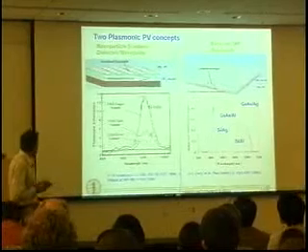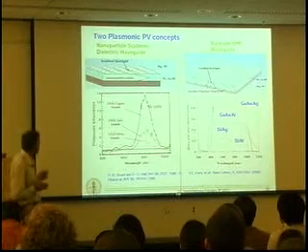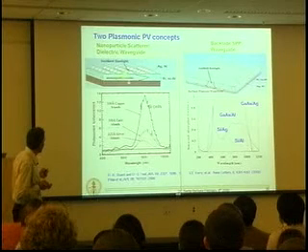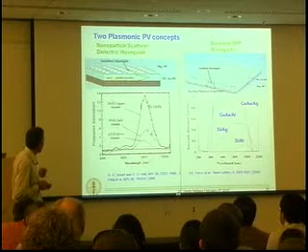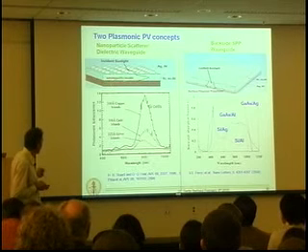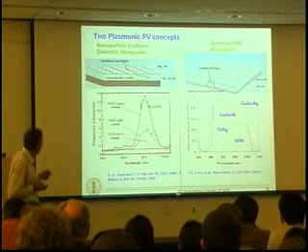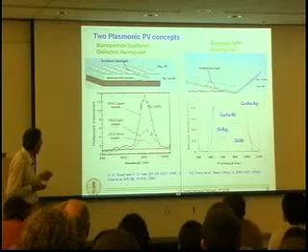So in photovoltaics, we're interested in exploiting the role of plasmonics in two ways, one of which is to use localized metal particles as scatterers to scatter light into dielectric waveguide modes of semiconductor films on low-index substrates. You might think of this like an integrated photonics waveguide, or to scatter into films that are coated on the back surface with a metal film here.